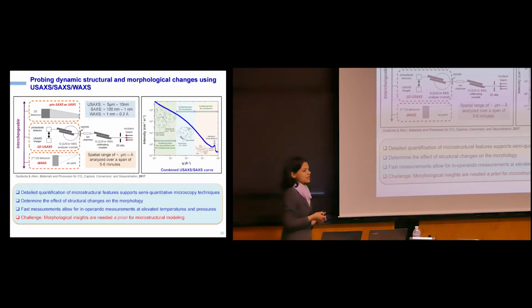We also wanted to understand what is happening to these materials, so we started harnessing ultra-small and small angle X-ray scattering measurements. For those of you who are familiar with scattering, and some of you who are not, basically the principle is that when you try and scatter materials that have very ordered crystal structures, that is using wide-angle X-ray scattering, you get a crystal signature of these materials, right? That's basically X-ray diffraction or wide-angle X-ray scattering. If you scatter from slightly larger length scales, then you start to get some insights into the nanoscale morphology of these materials. If you scatter from some of the larger length scales, now you're approaching some of the micrometer-sized features that you can extract.